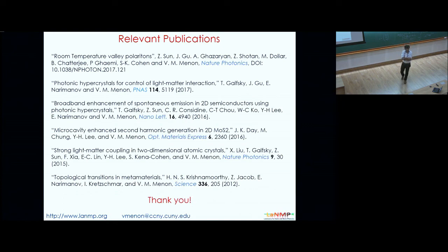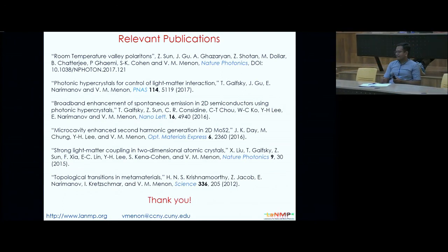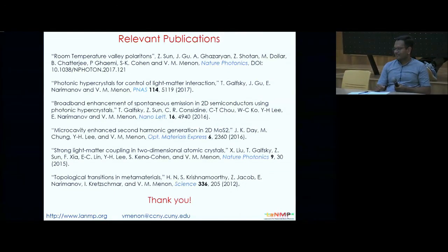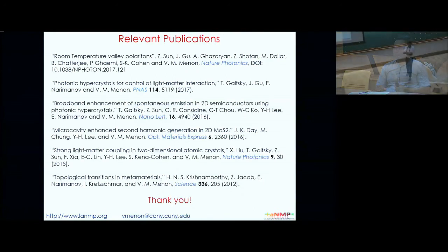Yes, so you have to start with a material that is already bad, with a lot of defects. We buy it from a company called Graphene Supermarket, so that should give you an idea of how bad the materials can be. If you get the boron nitride from the famous Japanese group, then you don't see these emitters.